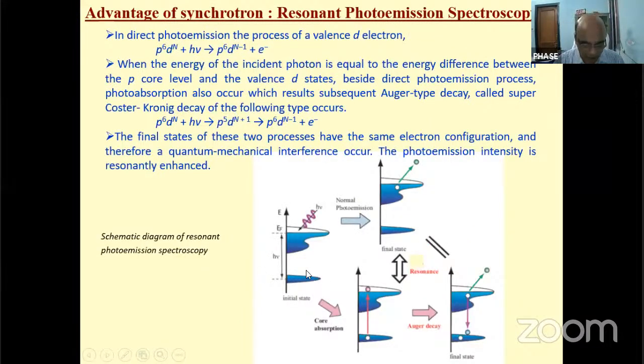Another advantage of synchrotron-based photoemission spectroscopy is that you have tunable photon energy. Normally in the laboratory, you have the helium-1 source or helium-2 source, which have a fixed photon energy, or you have the aluminum K alpha or MgK alpha source, with 1200 or 1400 eV photon energy. But here, because the synchrotron gives a continuous energy range, you can tune the photon energy depending upon the absorption edge of your sample. And because of tuning the photon energy, one can get resonance in your photoemission spectrum. Because of the resonance, the intensity gets resonantly enhanced, one can get a good quality spectrum, and one can analyze that type of problem.